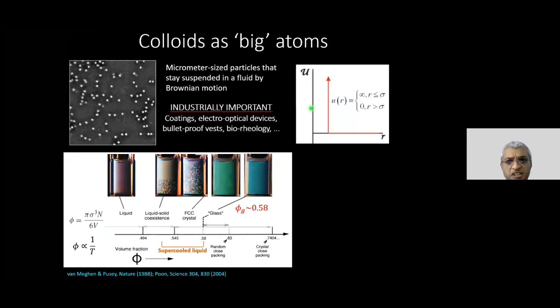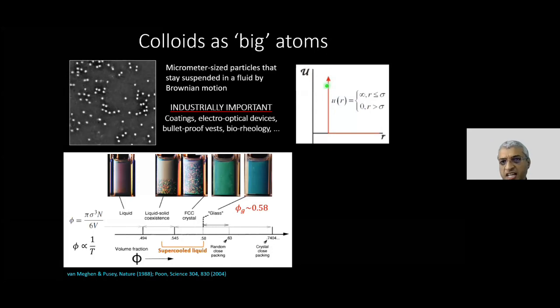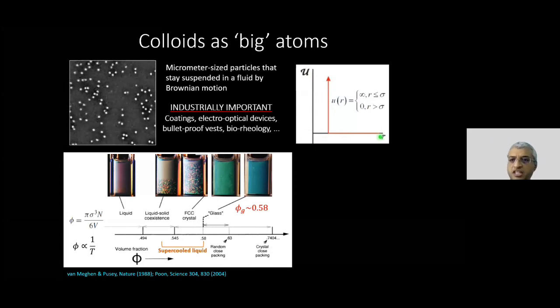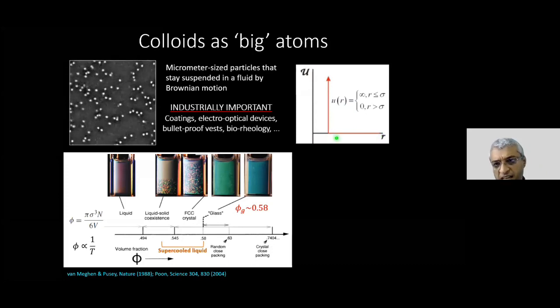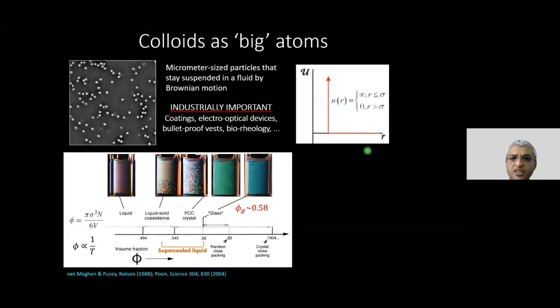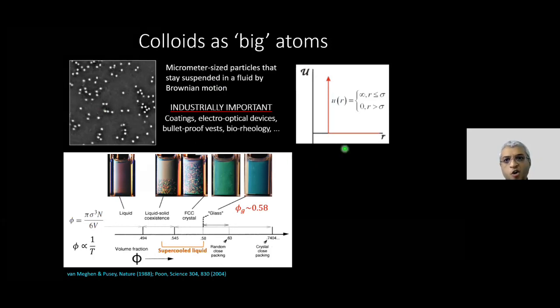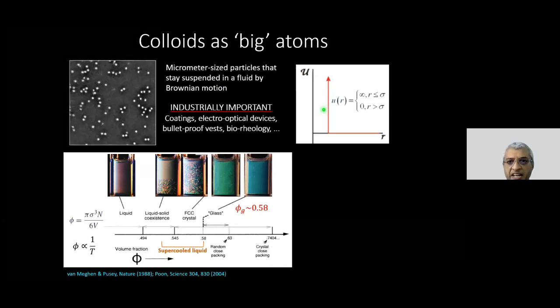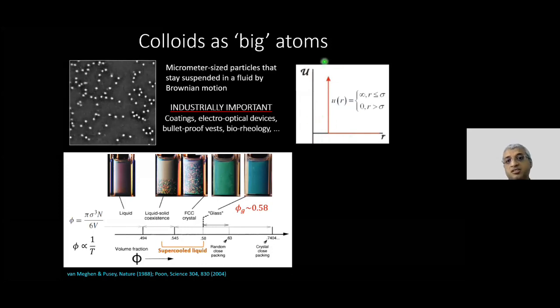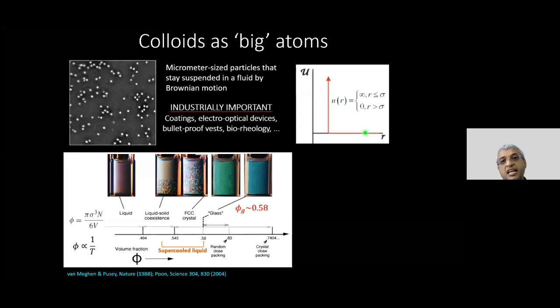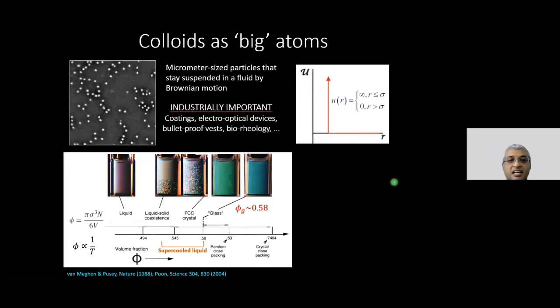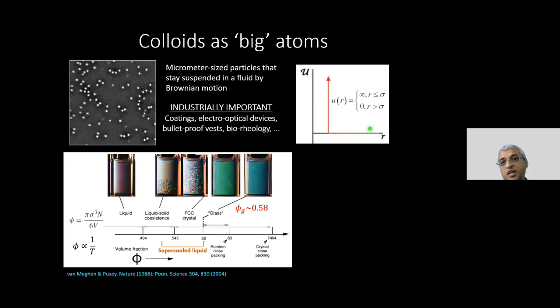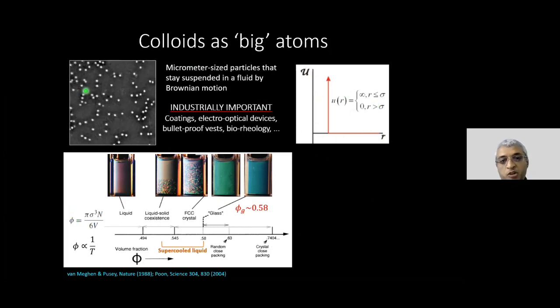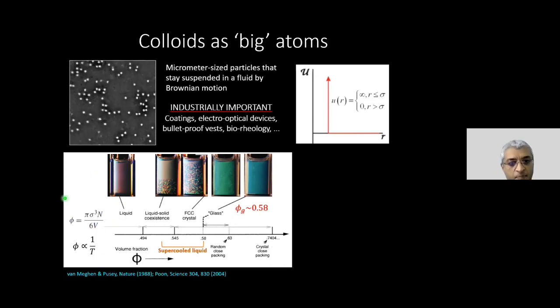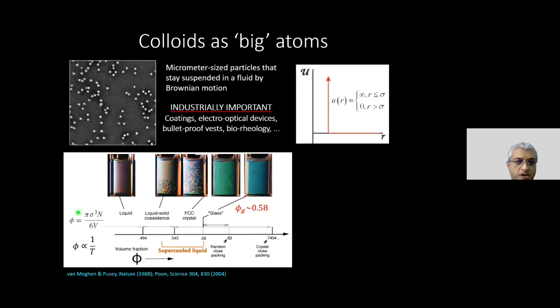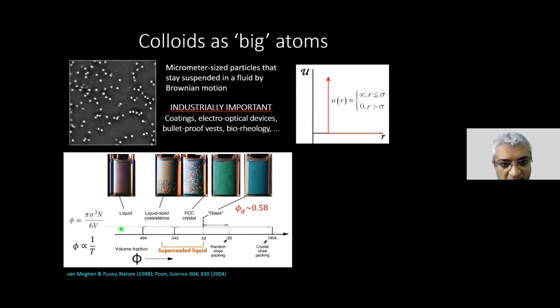Now, if I were to take the simplest of the interactions, which is basically what I call a hard-sphere interaction, the interaction is basically 0 beyond the particle size, and it is infinite at contact. Okay. Now, it turns out that colloids are the closest mimics of hard-spheres that you can experimentally realize in a lab. And because the potential looks like so, thermal energy simply doesn't matter. The phase diagram is entirely going to be decided by just the number of particles I'm able to pack in a given volume. Okay, and that parameter is called the volume fraction, which is just the volume occupied by the particles divided by the volume occupied by the container.